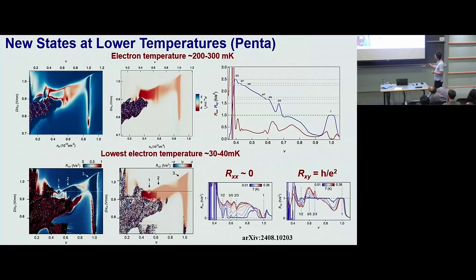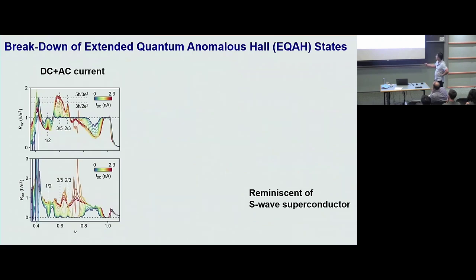Okay? A little bit more on this: integer, very fragile. You need very low temperature to see it. You actually also need very low current excitation. What I'm showing here is that you can apply a DC current background plus an AC current modulation. And then you can vary the DC current. You keep the AC part very small, and you can vary the DC current from 0 to something like only a couple of nanoamps. That's big enough to cause a qualitative difference.